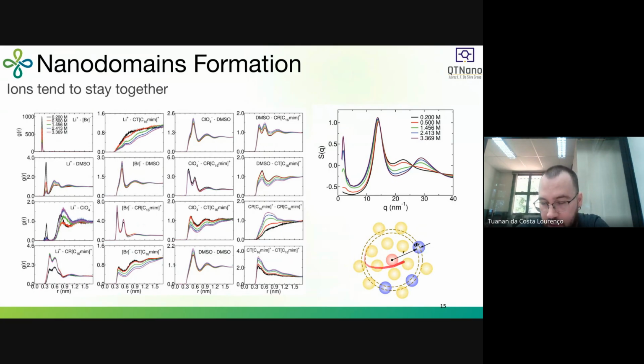In the chart on the right, we have a central molecule that we call the reference molecule. When we calculate the RDF, we are looking at the probability distribution of the molecules around the reference molecule, as I go to increasing values of r. So this is my central DMSO here. If we look at the plot, at 0, I have 1 DMSO. When I go walking, nothing happens. When I reach 0.3, we see the peak increasing. And this peak represents the first solvation shell around DMSO. So this peak is this structure here.